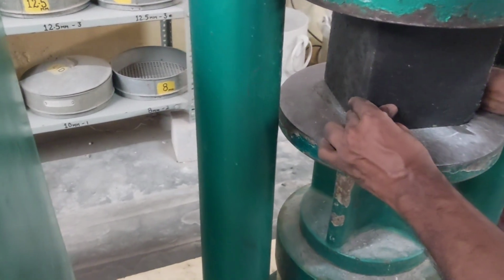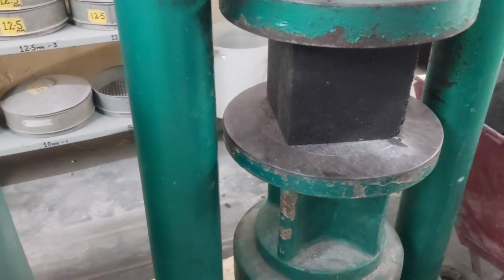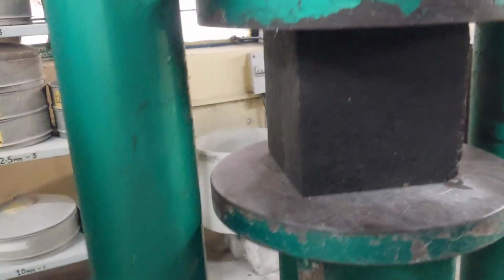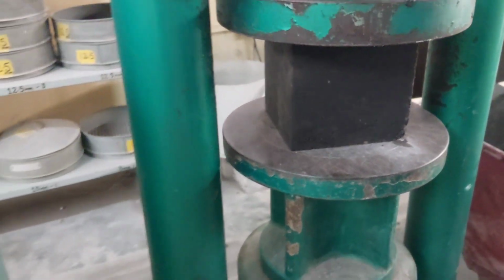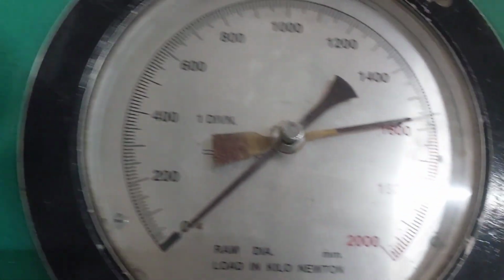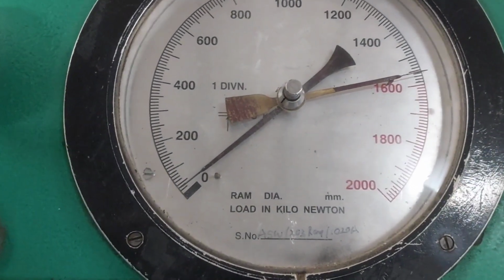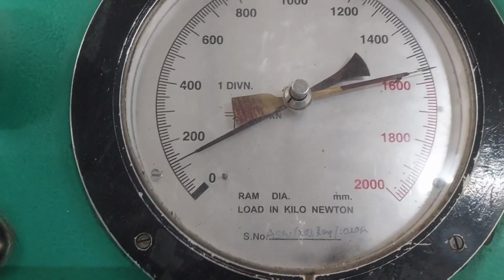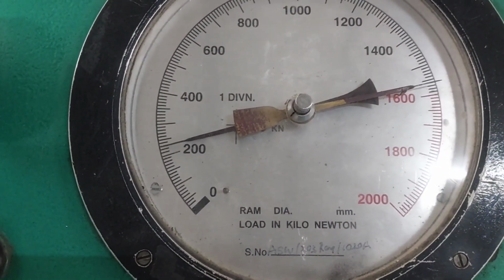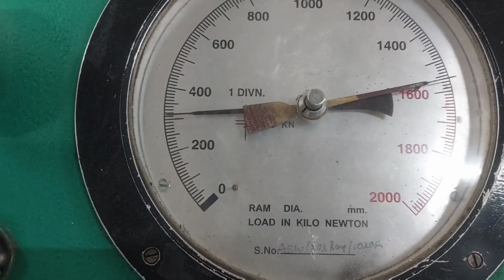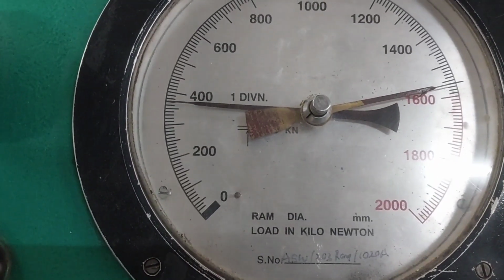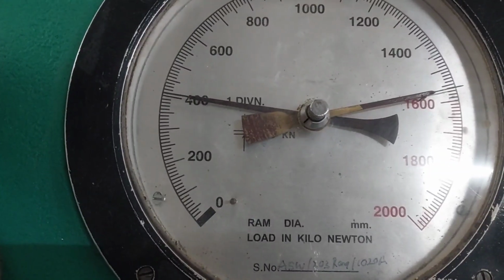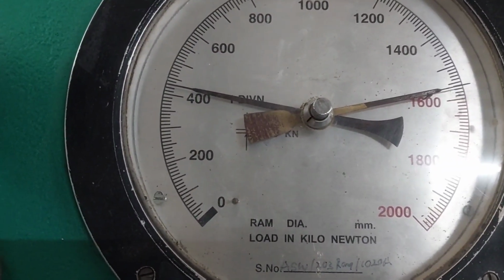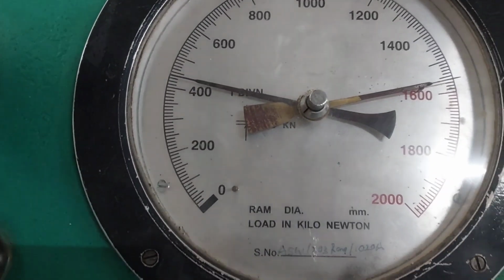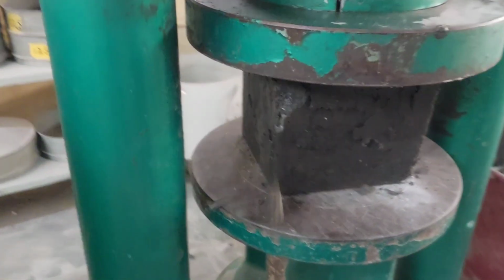Similarly, by placing the third cube, we gradually apply the compressive load in the compressive testing machine to the maximum load at failure, and next we calculate the load in kilonewton. So this is how the load gradually increases up to ultimate failure. Now you can see after 0 the load gradually increases for the third standard cube up to 250, 300, 390, 400, and up to 430. So this is also 440. The maximum load taken by this third standard cube is 430 kilonewton.